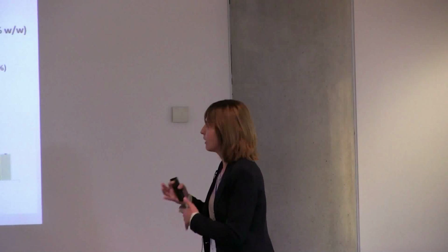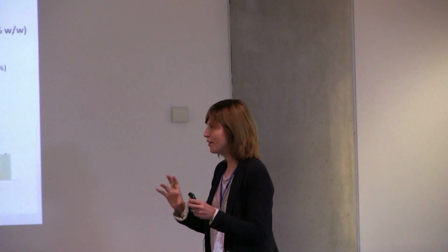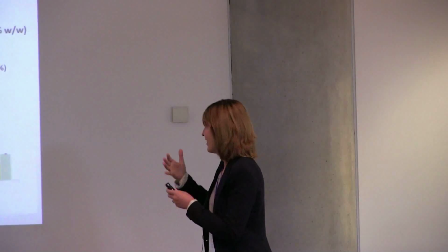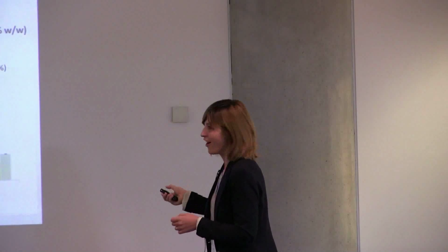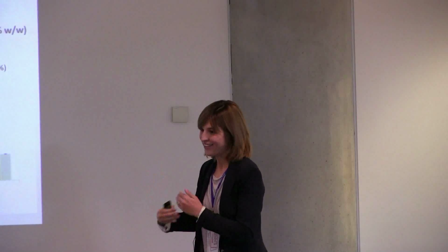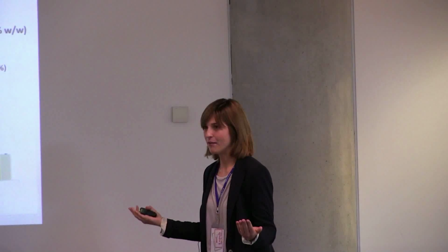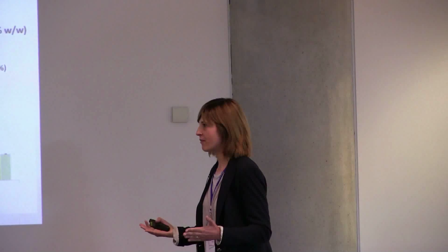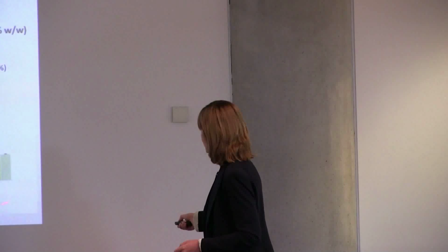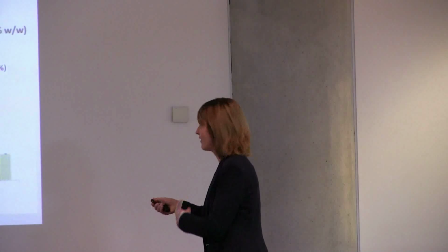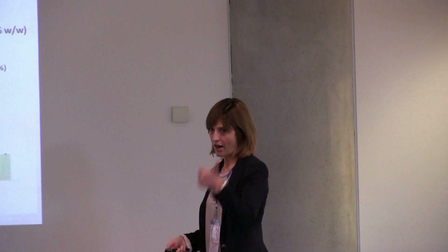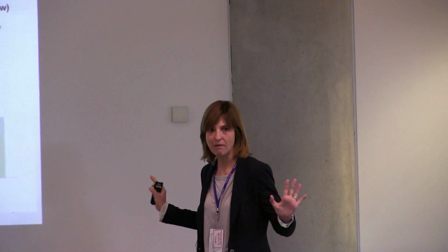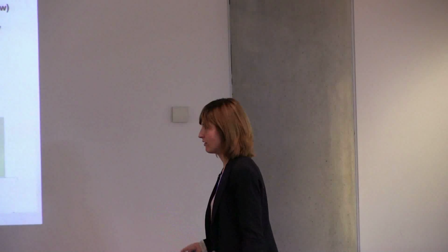But we also studied how reddish the samples were. And here, the most relevant, of course, is that if we add more oil, we are adding more beta-carotene, so the samples are more red. But if you see here, nanoemulsions with 2% of pectin and 4% of oil were substantially less red than the others with 1%. So they are more transparent and less red, and that can be good for some applications. We don't know, it depends. Okay.